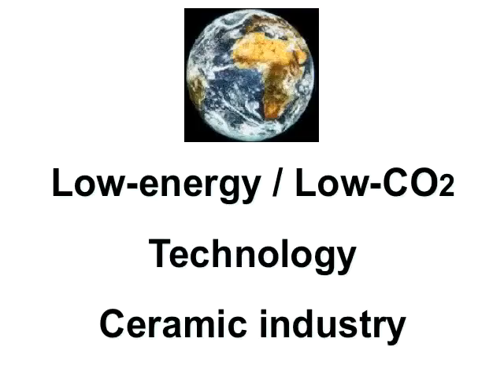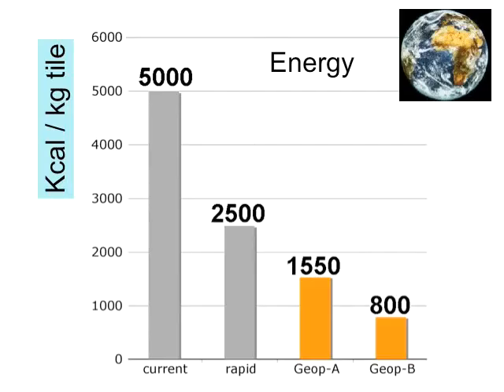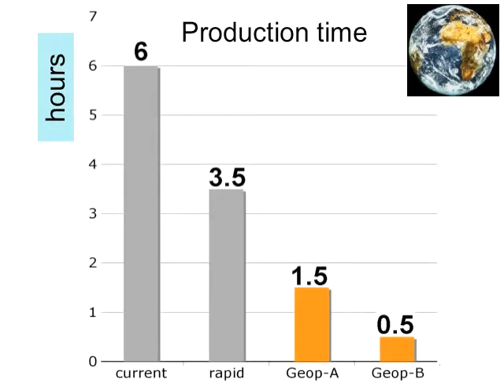One of the major results, we had several posters, but one which is really striking is the following one: low energy, low CO2 technology for the ceramic industry. If you look at the energy consumed to make a tile with geopolymer chemistry, you divide the energy by 5 or 6. If you look at the production time of a ceramic tile using geopolymer chemistry, you divide this time by 12 or by 4.